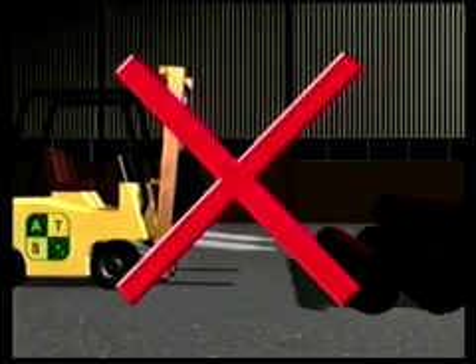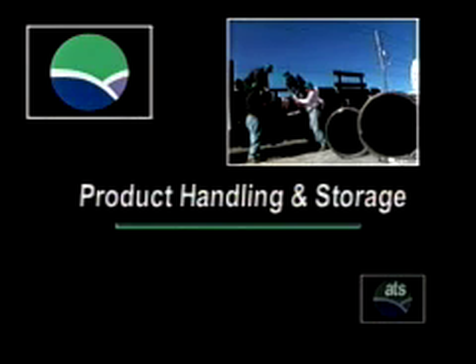Keep the duct from rolling over rocks or other objects. As the duct rolls over or against them, the pressure point on the outside surface transfers the energy of the weight of the duct to a single point on the inner liner at the point of contact. This may cause spider cracks in the inner liner. If so, repairs would be necessary to restore the integrity of the corrosion barrier. See our catalog for repair procedures if you detect damage to the inner liner.